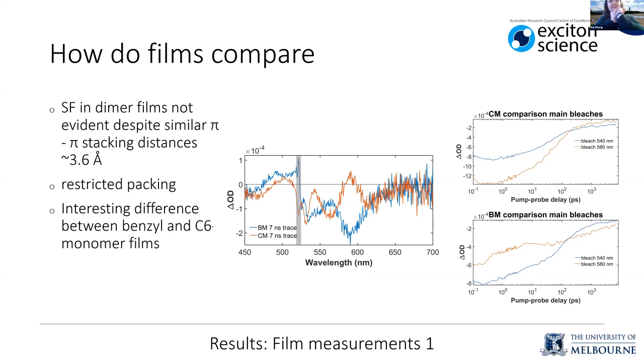I also found that it's quite different spectral behavior. Well, the spectra look quite different for the benzyl monomer compared to the flexible monomer. And what's interesting is that here I have the two main bleaches in the transient absorption for each of these monomers. And in one case, the bleach that lives the longest, so the bleach that would be leading to the singlet fission process, seems to be in the lower energy bleach. And in the other case, it's in a higher energy bleach.